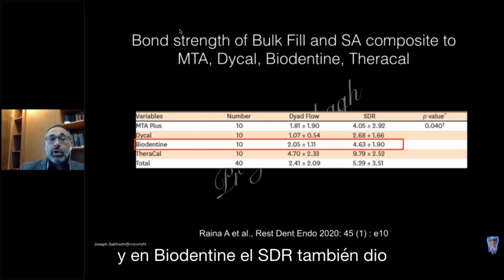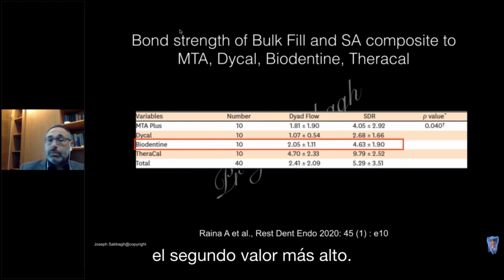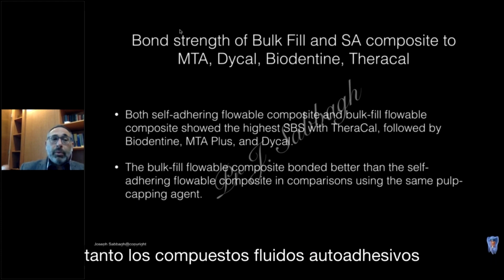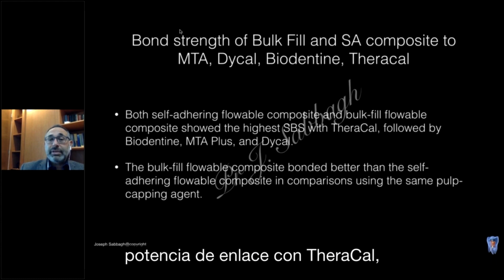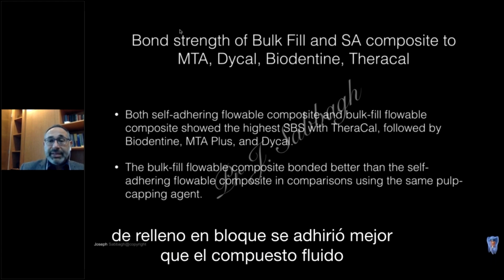We see that the TheraCal gave the highest bonding adhesion values, and on Biodentine, the SDR gave also the second highest value. So this proved that we have good adhesion between those materials. Both self-adhering flowable composites and bulk fill flowable composites showed the highest shear bond strength with TheraCal, followed by Biodentine. And the bulk fill flowable composite bonded better than the self-adhering flowable composite in comparison using the same pulp capping agent.